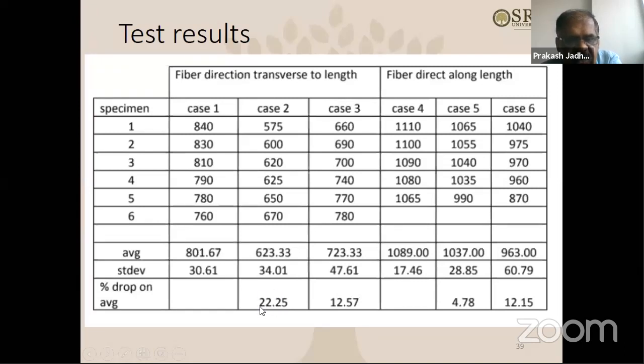Okay, why is this drop there? Just by changing the location of ply drops. So the location of ply drop is very, very important. So when you design any structure with ply drops, this factor has to come into importance. And that's what we did in this design space study, that if you have a different location of ply drop, how